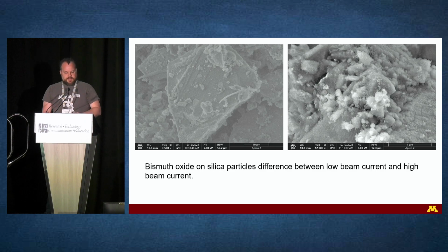You see a lot of topography, but we don't get very much chemistry. As we turn the beam power up to higher currents, we get proportionally more backscattered electrons on the right-hand image, and the brighter particles are actually the bismuth oxide on top of the silica. So this was very helpful for them to see the distribution of their catalyst on the silica substrate.